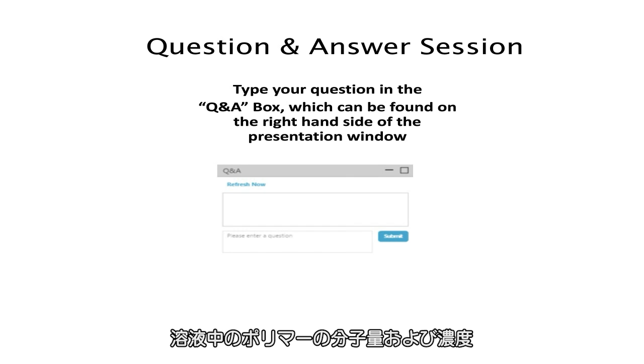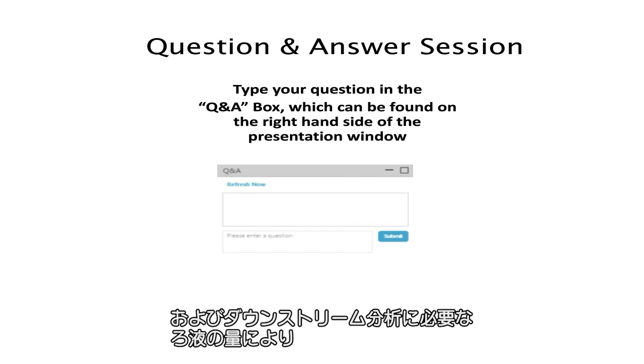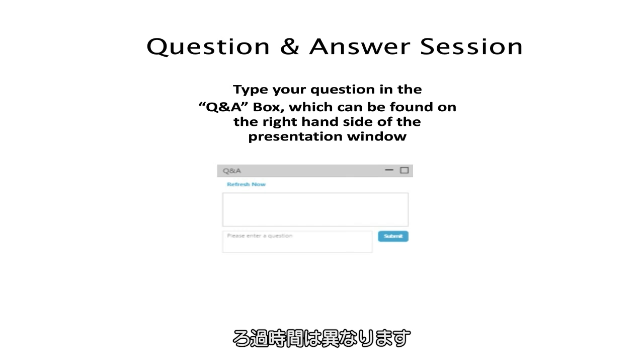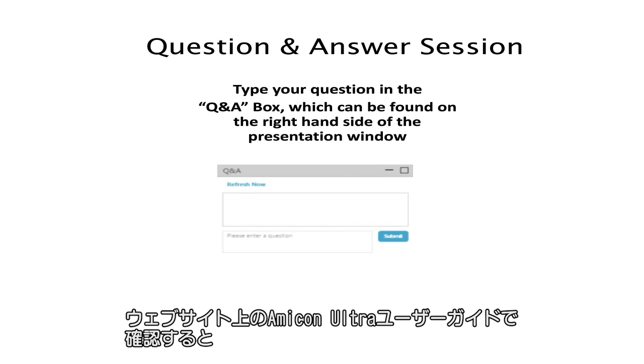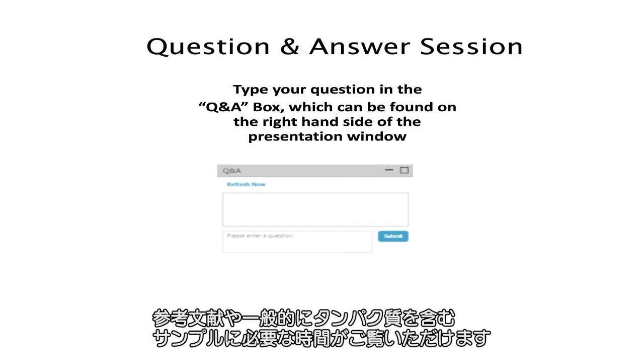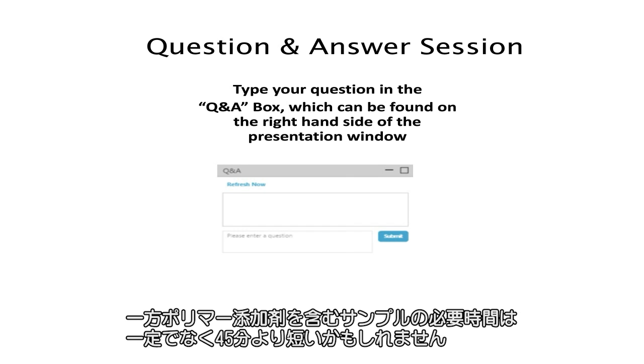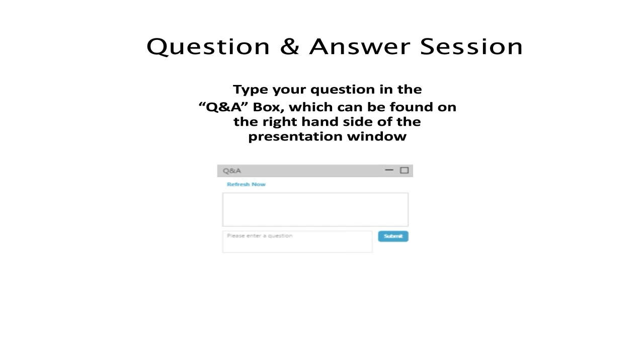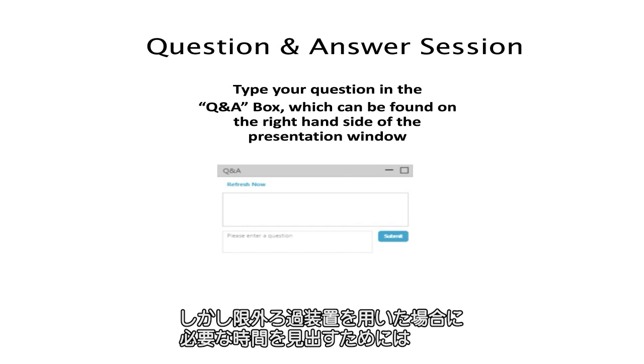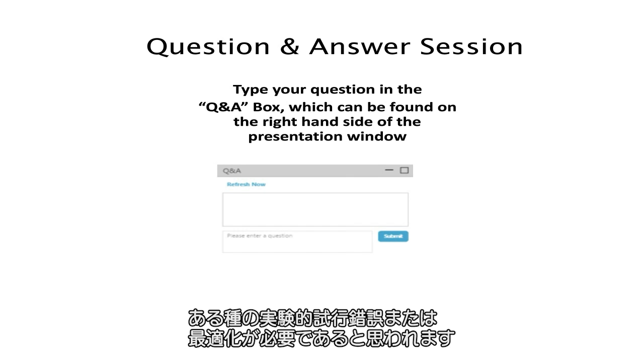So depending on the molecular weight of the polymer and the concentration of your polymer that is present in the solution, as well as the amount of filtrate that is necessary for the downstream analysis, the filtration time might vary. If you look at the Amicon Ultra user guides on the website, the time requirement is generally provided for samples containing proteins, whereas with samples containing polymeric excipients, the time required may be different or may be smaller than 45 minutes. But there would need to be some kind of experimental trial and error or optimization before you can come up with a time that is needed with ultra filters.